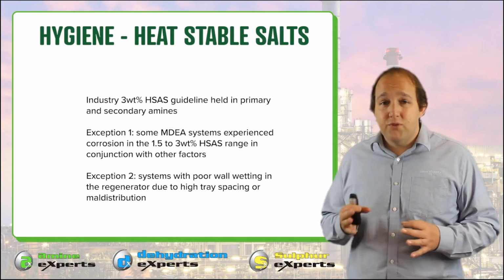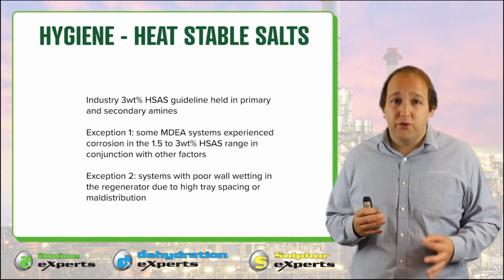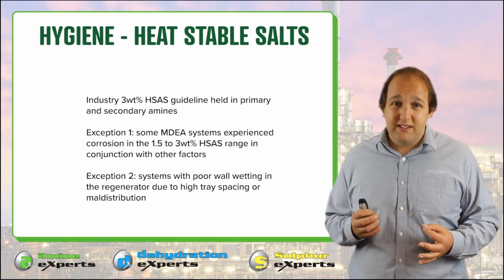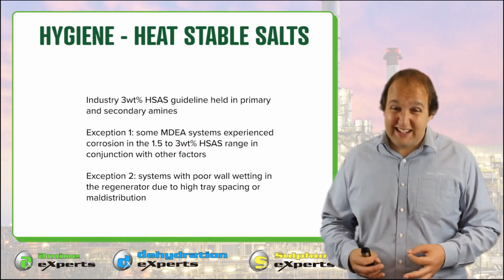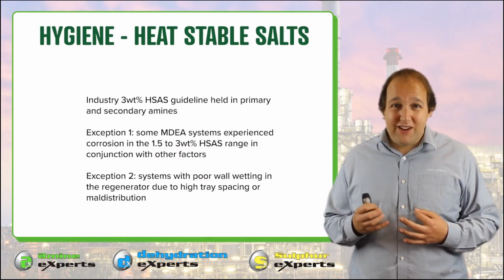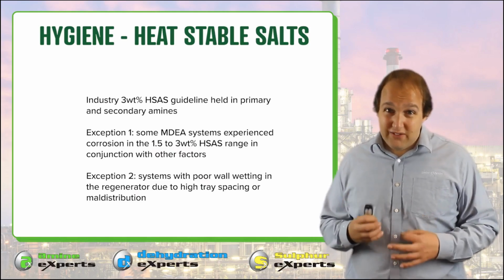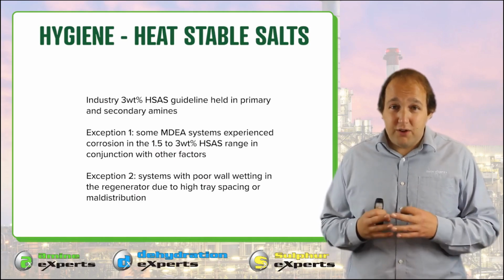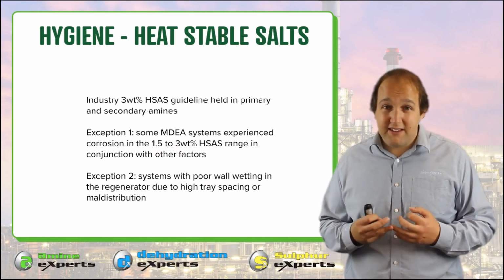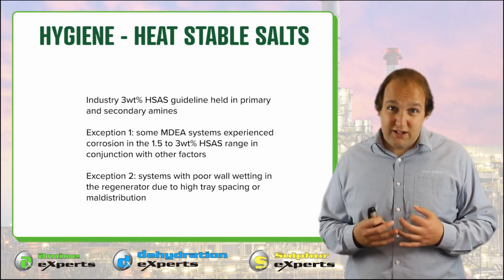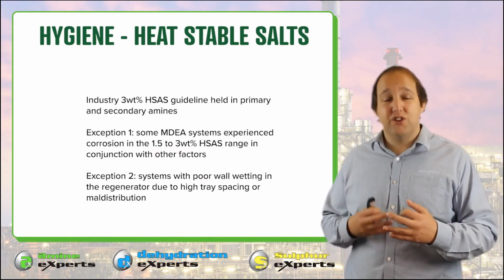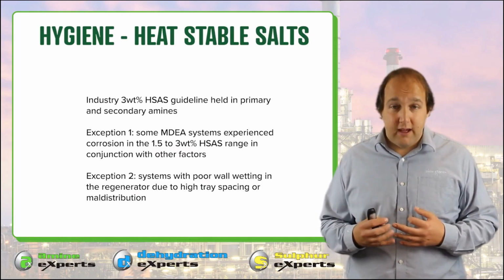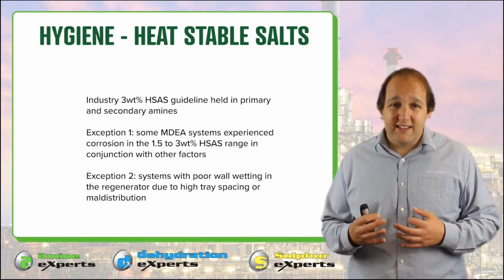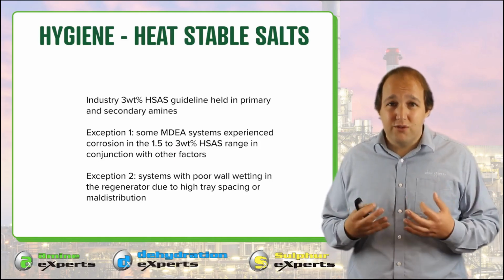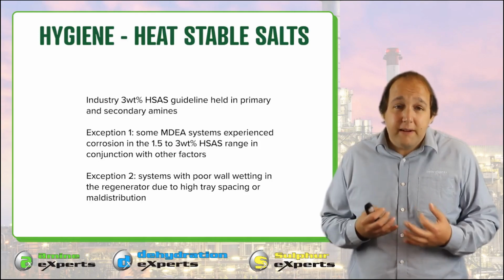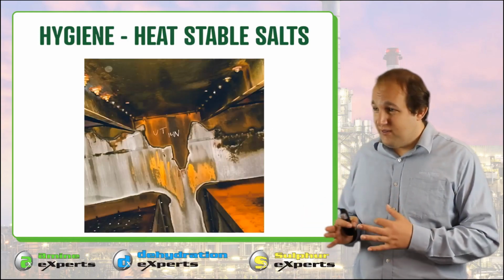Now, the other dominant main cause of corrosion that we see in amine systems is high heat stable salts. Briefly, heat stable salts are acids that are stronger than H2S and CO2 that have entered your system, and they bond to the amine. Because they're stronger, that amine-acid bond doesn't easily regenerate, so it's called heat stable. It doesn't regenerate, it just accumulates in your system. And when the levels of these acids rise too high, the solution becomes corrosive, and typically it'll look something like this, like a lake of corrosion.